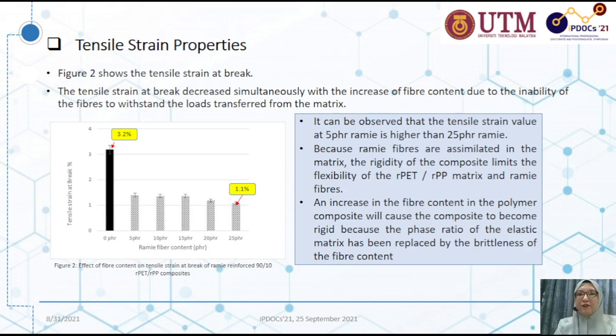The rigidity of the composite limits the flexibility of the recycled PET, recycled PP matrix, and ramie fibers. An increase in the fiber content in the polymer composite will cause the composite to become rigid because the phase ratio of the elastic matrix has been replaced by the brittleness of the fiber content.